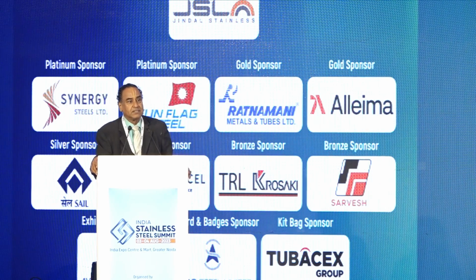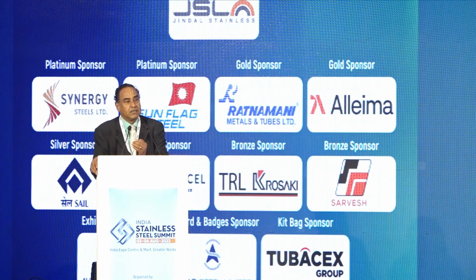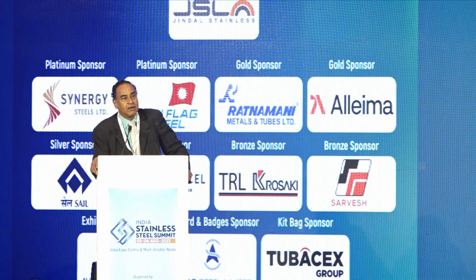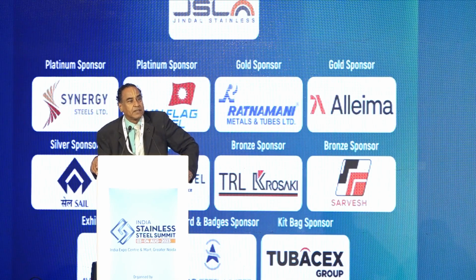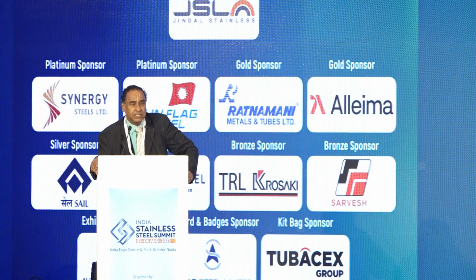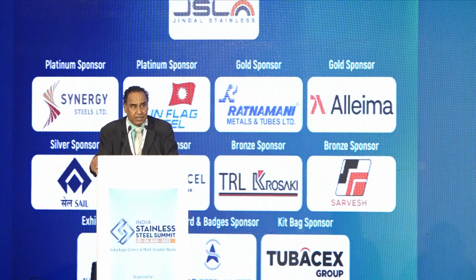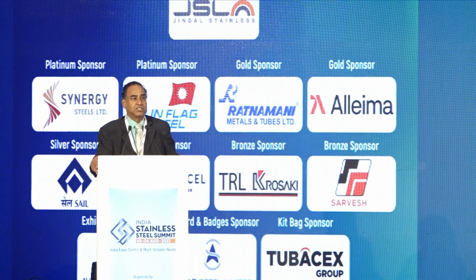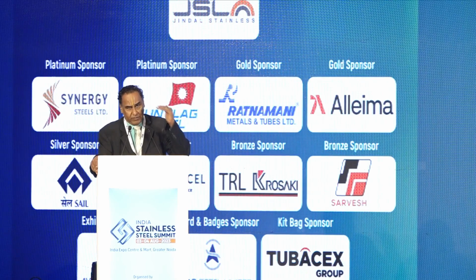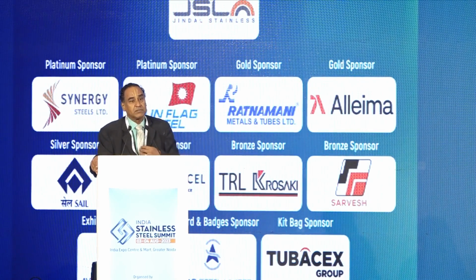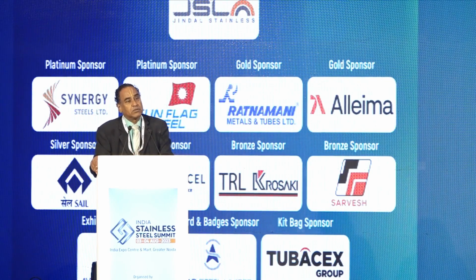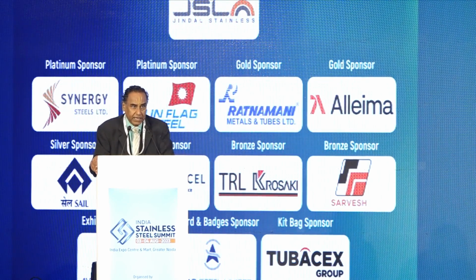A similar exercise is done, then, for high alloy steels. The next alternative is lean stainless steels, which have much lower corrosion resistance requirements because of the presence of chromium, which forms a very tenacious and continuous layer. Basically, it's a corrosion layer. Chromium becomes chromium oxide, and when it is continuous, impervious and tenacious, it stays permanent. It prevents further corrosion beyond that layer. Because of that, it's stainless in nature. That particular material is chosen so as to avoid the corrosion allowance completely.